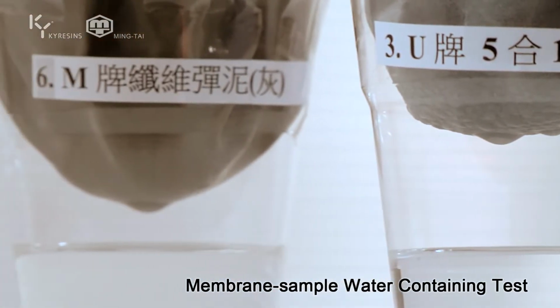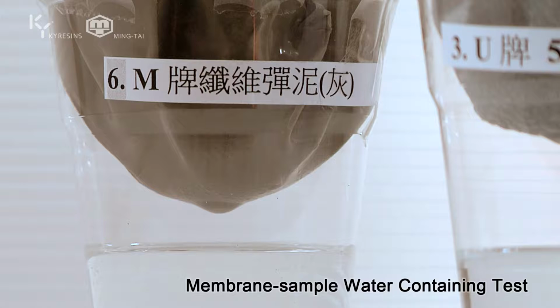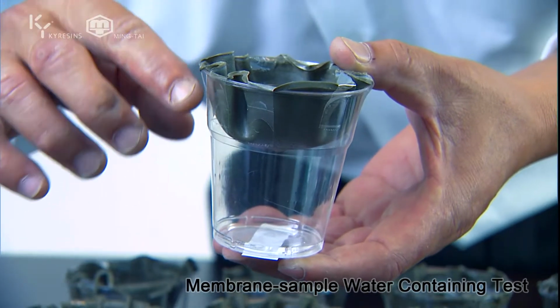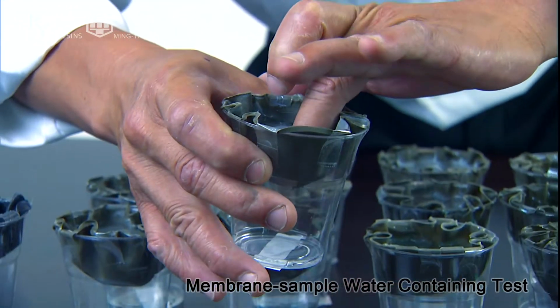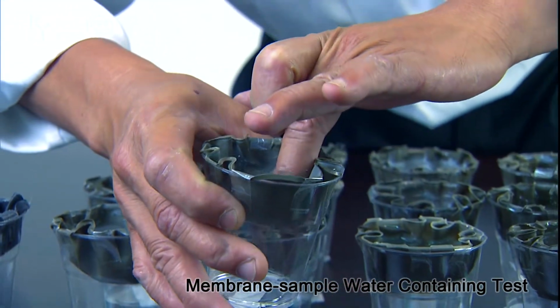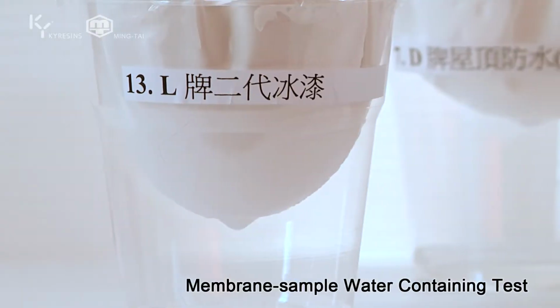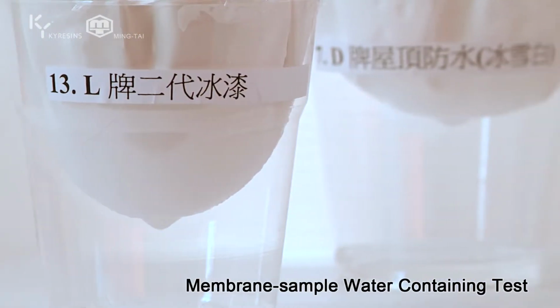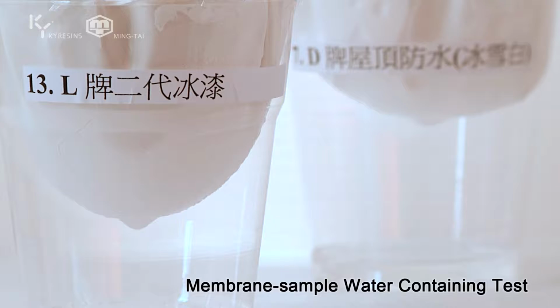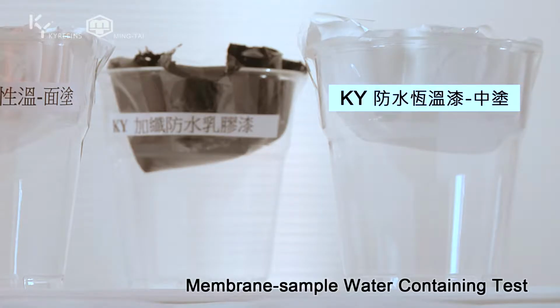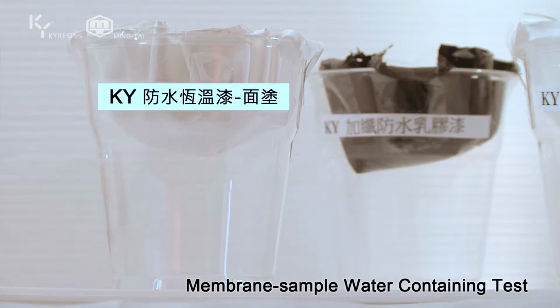After 24 hours of soaking, most of the waterproof paint had water penetration down to the container bottoms due to the component of emulsifiers, even though the membranes had not broken. That is why most of the waterproof paint were not really water resistant. Only KY patent waterproof paint and patent constant temperature paint passed the harsh tests with the super effects of water resistance and deterioration free.